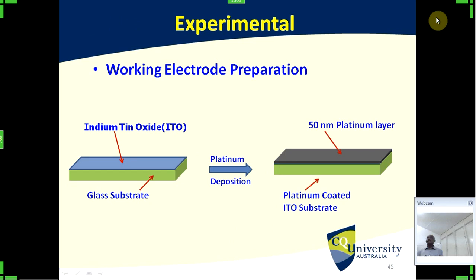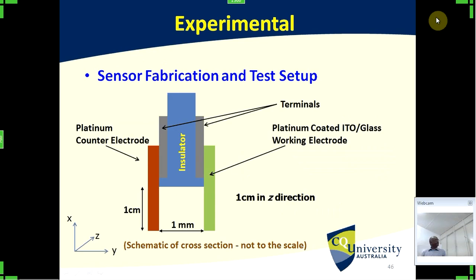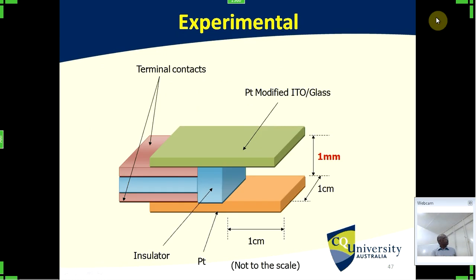To test the effectiveness of the corrugated surface, we again used the flattest surface which we can find. That's the ITO substrate. It has glass substrate and indium tin oxide deposited on one side. After platinum deposition, it gets 50 nanometer of a platinum layer on top of the ITO layer, so that we can develop the polypyrrole on top of this one. This is a schematic diagram of the experimental setup. I used 1 millimeter distance between these two electrodes, and this electrode with platinum deposited inside this one, and this was connected to the electrochemical deposition system and pulsed. So this is another view of the same.